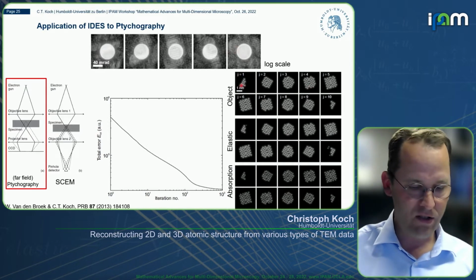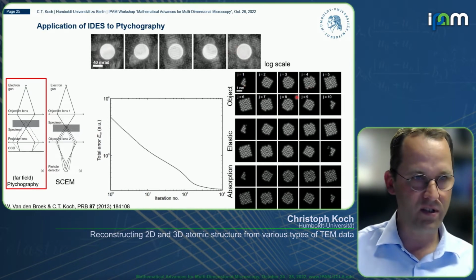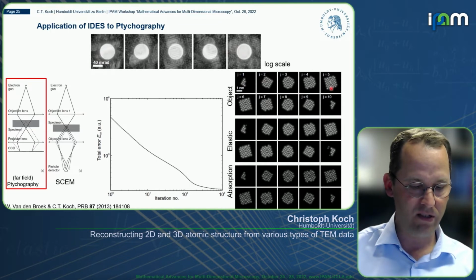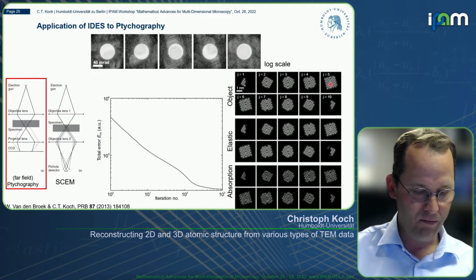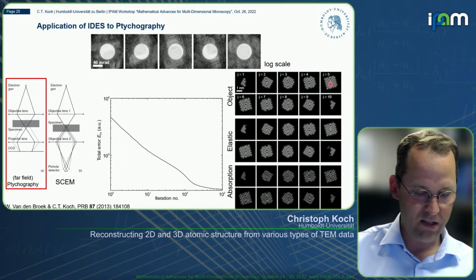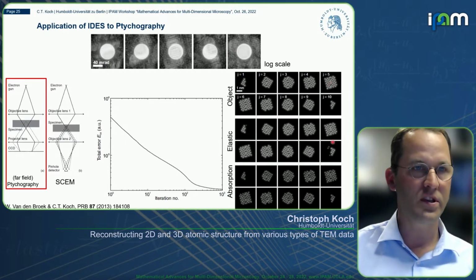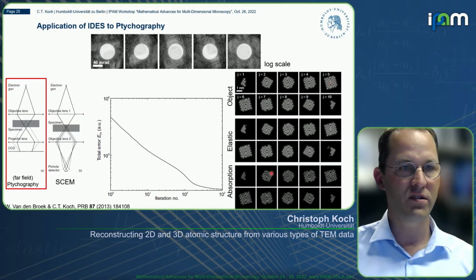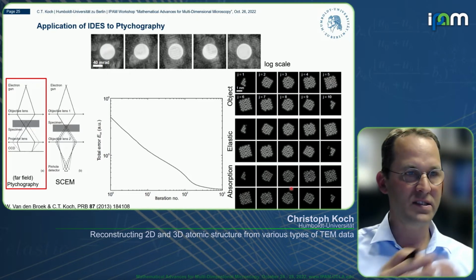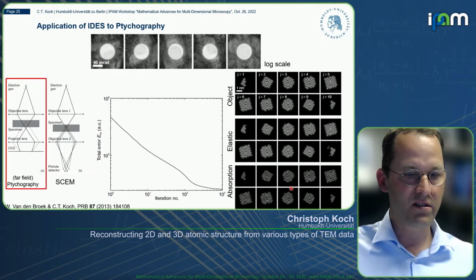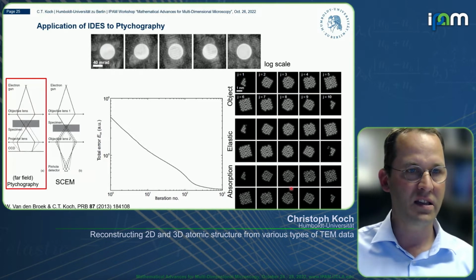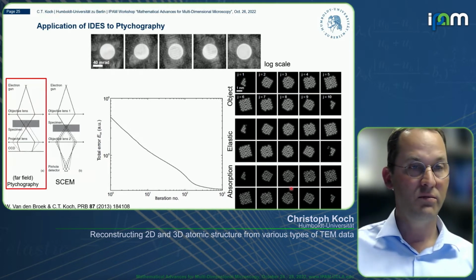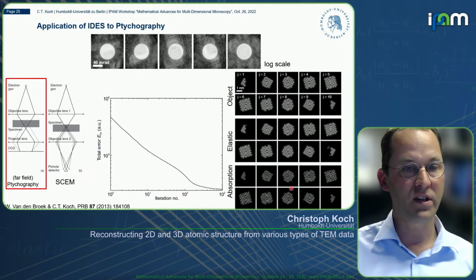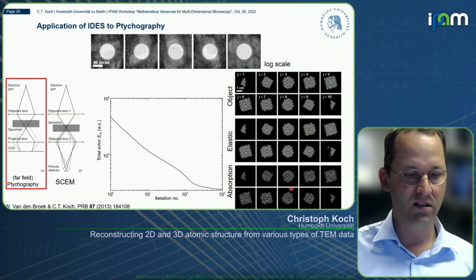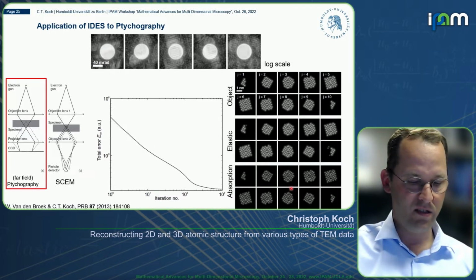So not just the phase shift, also in the high resolution case, that was the same, I just didn't show that, but both the elastic scattering potential and also an absorptive part of the potential, that means an imaginary part of the potential, accounting for scattering outside of your detection system, or really exciting some inelastic excitations, which then, because you assume zero loss filtering, scatter outside the elastic channel and with that not into your recorded data anymore.